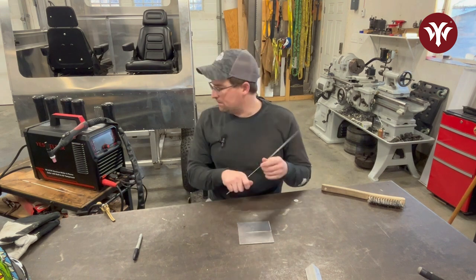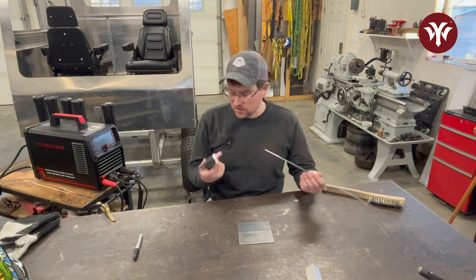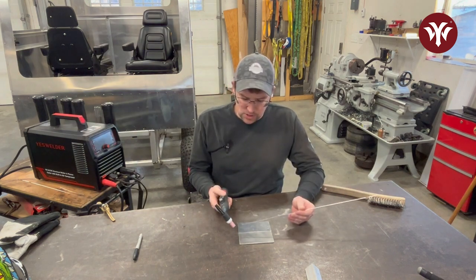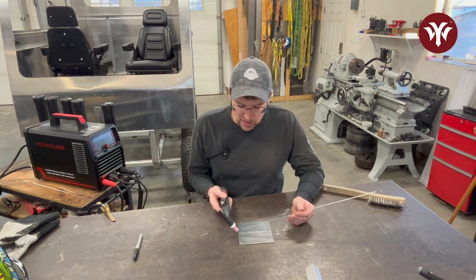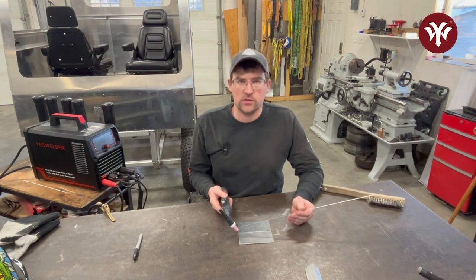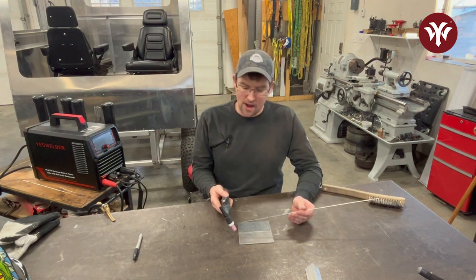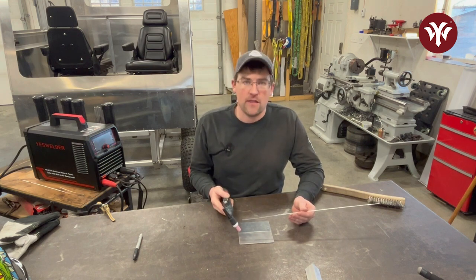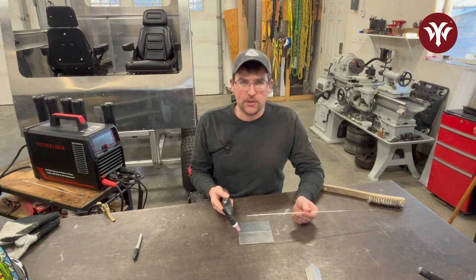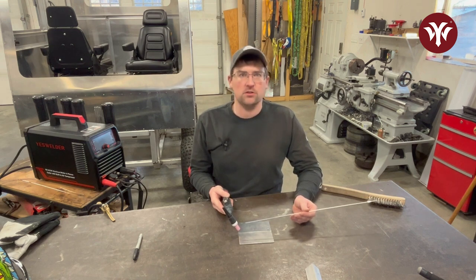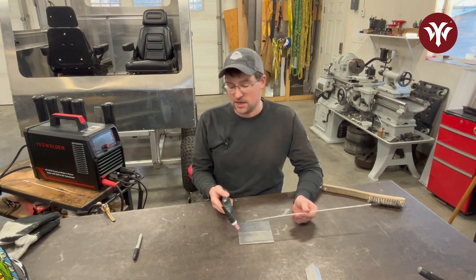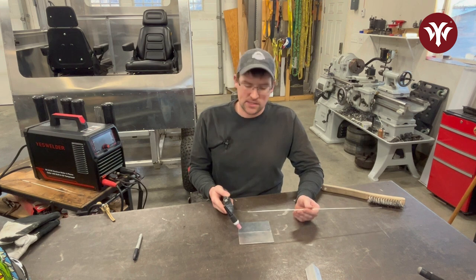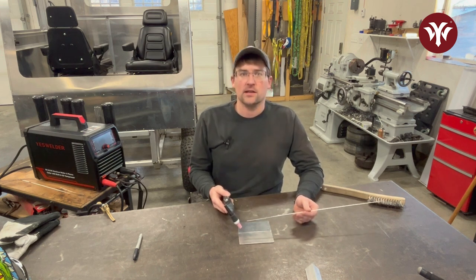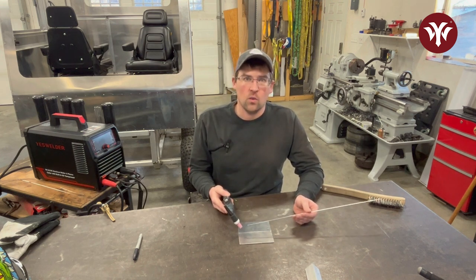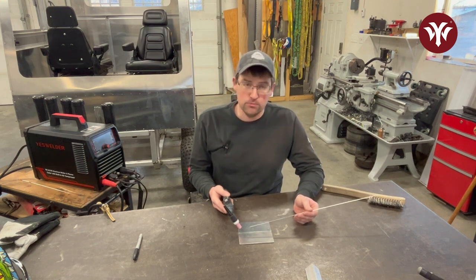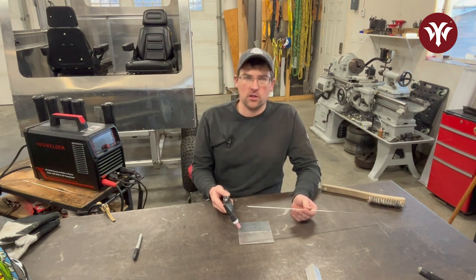And when you're running a pulse with a TIG, it's gonna pulse on, and when it's pulsed on, you dab your filler rod when it's real hot, and then the pulse is gonna back off, and that's when you move the torch. And then the pulse comes on, brings that puddle back to life, you'll dab in your filler rod, and then the pulse comes off, and it's just a process. Really, the pulse sets the rhythm for the weld, because you're only gonna add filler rod when the pulse is on, and you move when it backs off to the low current.